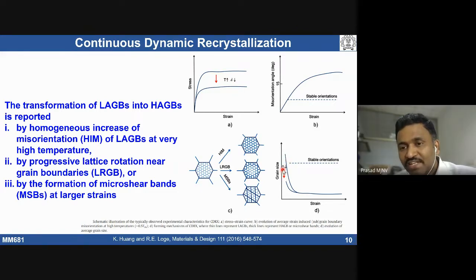Which grain size? Okay, D naught is the initial grain size. Initially I started with this grain size. For example, one grain is 100 micrometers, the other one is 10 micrometers. When I deform both materials, same material composition, only grain size is different, what happens with strain? We are going to end up with the same grain size. So it's independent of your prior grain size. The recrystallized grain, whatever develops under CDRX conditions, the size is actually independent of the prior grain size of the material.